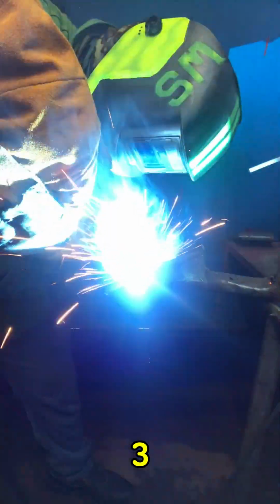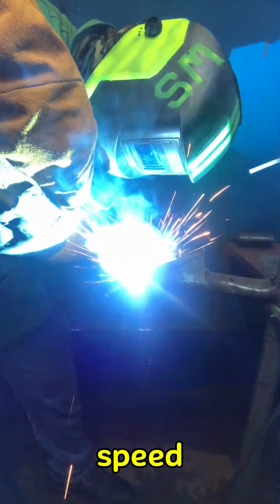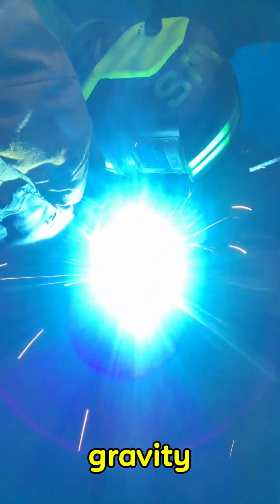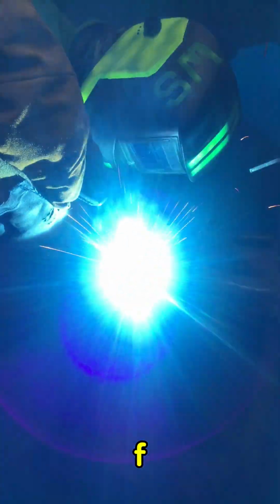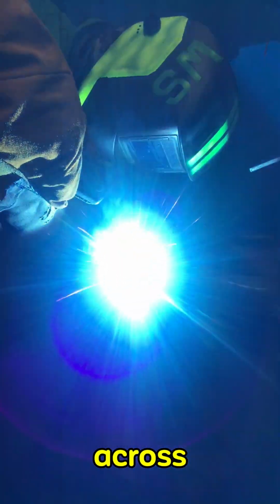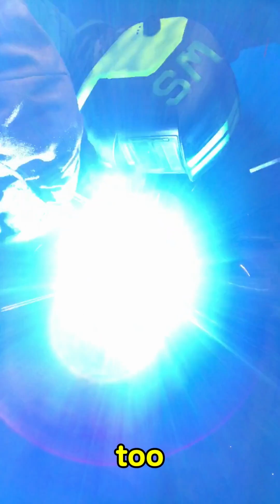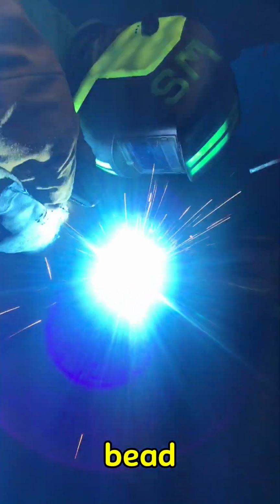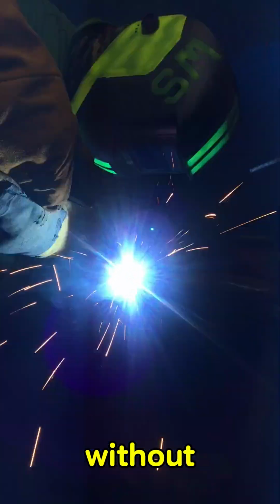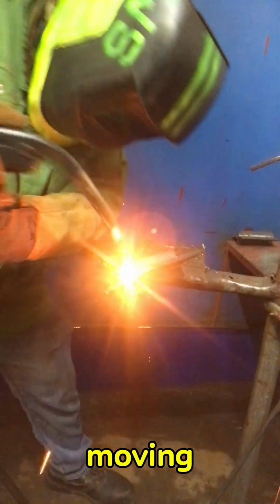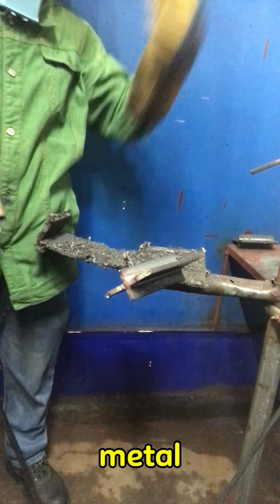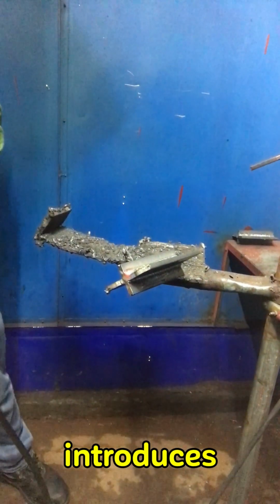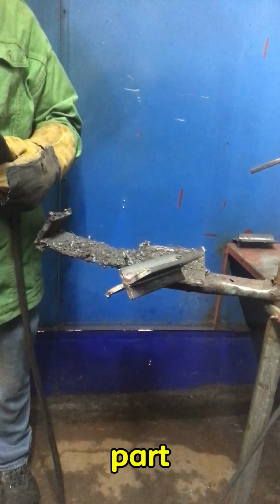Mistake number 3. Moving too fast or changing your speed constantly. Because gravity keeps the puddle level in 1F, it's tempting to drag the arc across the joint quickly. Moving too fast produces a thin, ropey bead that sits on top of the joint without penetrating the root. Moving too slowly builds up excess weld metal, wastes filler, and introduces unnecessary heat into the part.